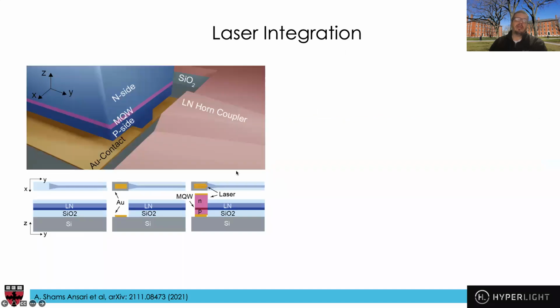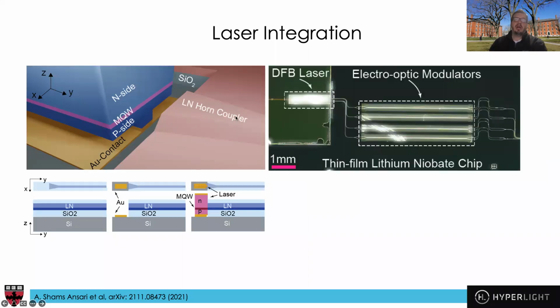The ultimate goal is to integrate lasers on the same lithium niobate platform, so we don't have to use optical setups to bring the light in. And we have demonstrated this recently. Basically, we use a flip-chip bonded distributed feedback laser on a prefabricated lithium niobate chip. Here's the top view. This is all lithium niobate with modulators realized. And then in one part of the chip, we etch a trench in which we bond the DFB laser. And this is all done with passive alignment.